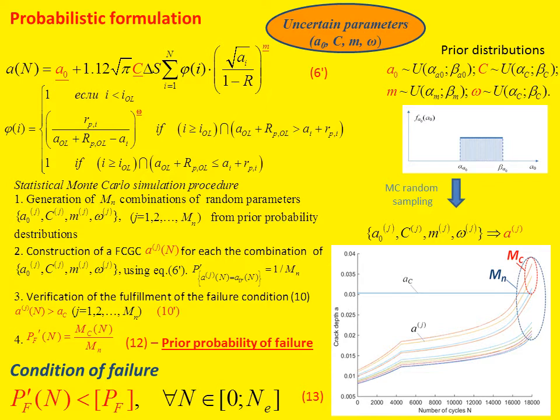After that, we have to draw a sufficiently large, say 10^6, number of samples from this PDF, or in other words, get a set of combinations of random parameters. Then for each combination, we can perform a numerical integration of equation 6' and get a set of fatigue crack growth curves. And for each curve, we have to check whether the condition of failure 10' holds or not.